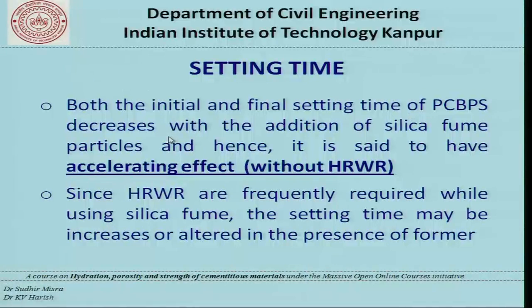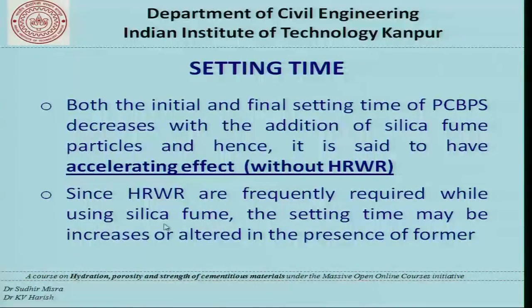Regarding setting time: both initial and final setting time of Portland cement based systems decrease with silica fume addition, indicating an accelerating effect. However, this applies only when no high-range water reducer is present. Since high-range water reducers are frequently required with silica fume, the setting time may increase or get altered in their presence.